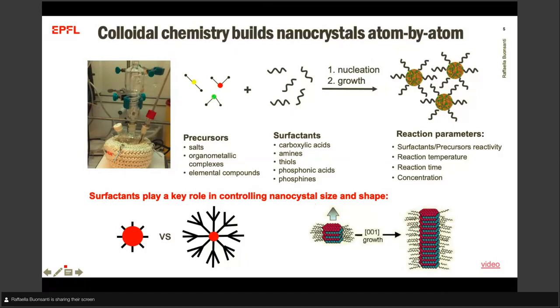And so we have this three-neck flask where we control the temperature, the atmosphere, we have a heating mantle, and we usually choose some metal precursors and surfactants, and then we control reaction parameters so as to obtain this monodisperse size and shape. And normally the surfactants or ligands play a key role in controlling the size. For example, highly sterically hindered ligands will normally give small particles, or the most trivial explanation for shape control is that they bind with different binding strength to different facets.